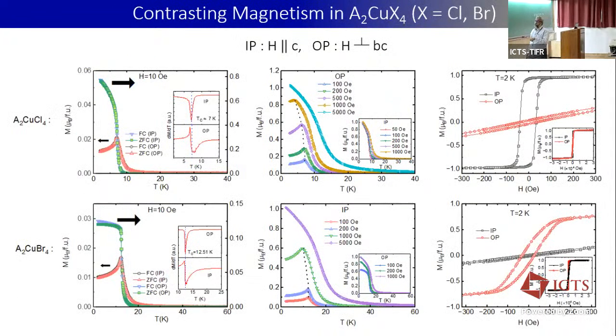Now this is one of the busy slides, but let me show you what I can in the time I have. In the chlorine case, the Tc is roughly around 7 K. But when you go to bromine, the Tc is around 12 Kelvin. But as I mentioned, when you go from chlorine to bromine, the copper-copper distance increases. Naturally, when the copper-copper distance increases, J should decrease. So naively one should think that in the bromine case, the Tc should be smaller. But here we get the Tc is larger. Because bromine is a bigger ion, the orbital overlap is more, that's why we get a larger Tc here.